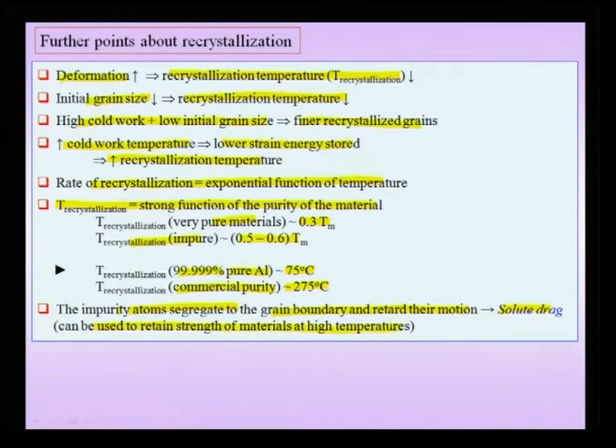So, what we are talking about here: suppose I had a pure material, this is my polycrystalline material, and therefore there are grain boundaries, and this grain boundary is pure. On the other hand, in a material of lower purity, you would find that there are some elements which tend to segregate at grain boundaries. Now, if this grain boundary has to move, suppose I have my grain boundary and there are solute atoms which have segregated to this grain boundary. If this grain boundary moves out, this implies that the solute atoms would be left inside the grain. This is an energetically unfavorable situation because these elements are typically not very soluble in the lattice.